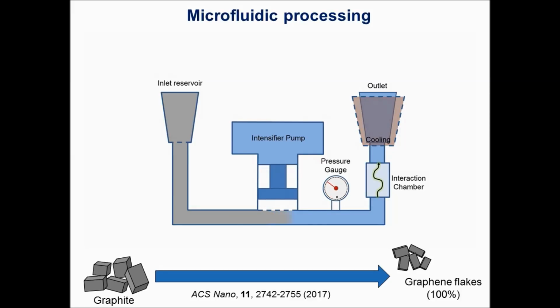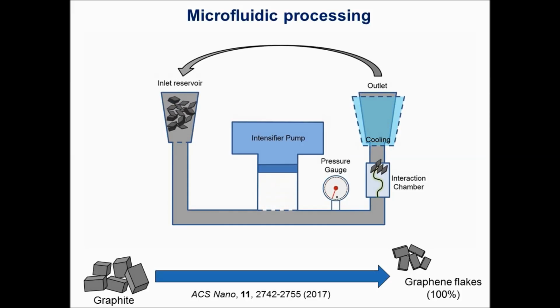So this schematic again just shows the process. As I mentioned, we have graphite coming in at the inlet reservoir, being pumped through the system. The interaction chamber is where all the exfoliation takes place, and then we recycle. So essentially we go from graphite to graphene flakes. We call them graphene flakes. These are flakes which are around 7 nanometers thick, around 1 to 2 microns in lateral size, but we are producing them in a 100% yield, and because everything is going through the same process and the same interaction chamber and being recycled, we end up with quite a uniform product at the end. Typically we are running the process for around 70 cycles to get the product we want, and I'll go into some of the characterization of the materials following this.